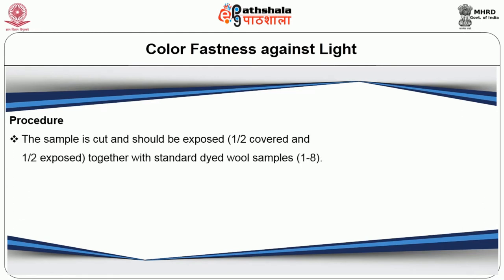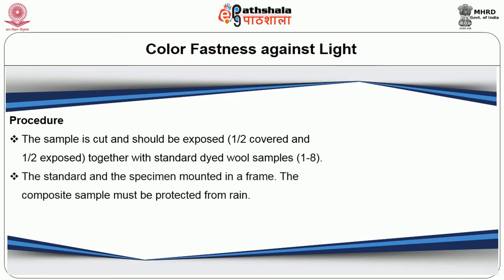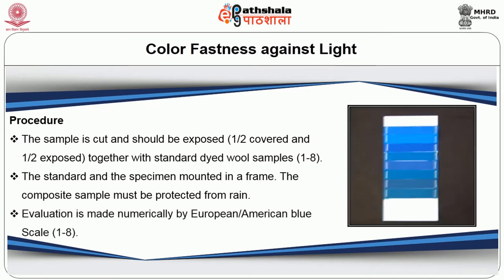Procedure followed: the sample is cut and should be exposed in such a way that part is covered and part is exposed, along with the standard dyed wool samples in the grade 1 to 8. The standard and the specimen are mounted in a frame. The composite sample must be protected from rain. Evaluation is then followed using the European or American blue scale in the grading 1 to 8.